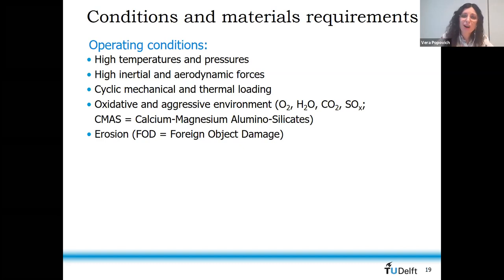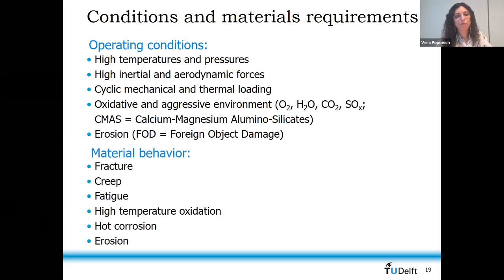Oxidation and aggressive environments, I mentioned to you that's not only the conventional oxidation, but that's also something like, for example, the sulfides, the corrosion degradation due to some sulfides. Calcium, magnesium, alumina, silicates, yeah? So this kind of degradation mechanisms in aggressive environments are common. Erosion, so degradation by a foreign object. And this gives us a range of materials behavior that needs to be accounted for.